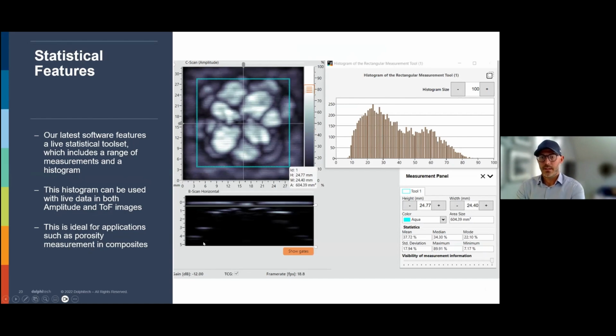Just to sum it up, our technology and tool is very easy to use, but at the same time, it can be used for a lot of statistical analysis and the like for the quality of the carbon fiber. Now, I've worked with carbon fiber for 10, 15 years with this ultrasound technology, and I've seen a lot of different qualities. Even using the correct frequency, you can also count the layers or how many carbon layers you have. And you can get a lot of data on the quality of your production, which I think is very interesting. This can be if there are wrinkles in your fiber, porosity in your fiber, or cracks in your fiber. You can inspect different geometries of carbon fiber, and you can also inspect carbon fiber in combination with other material.